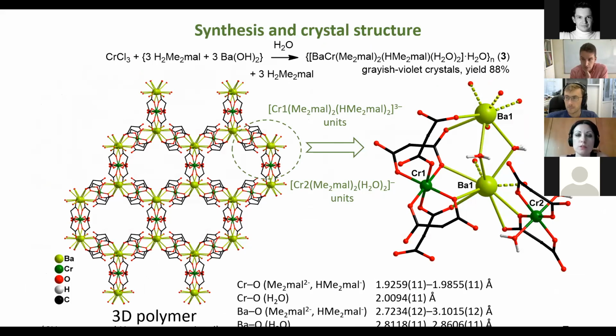Yes, the pore volume in compound 3 is about 7%. It was measured by mercury porosimetry. These pores are filled with water molecules, and when we heat this compound to remove the water molecules, it was found that the structure of these compounds degrades. And when we tried to measure the sorption properties for this compound, it turned out that there was no sorption because of the degraded structure. Okay, thank you.